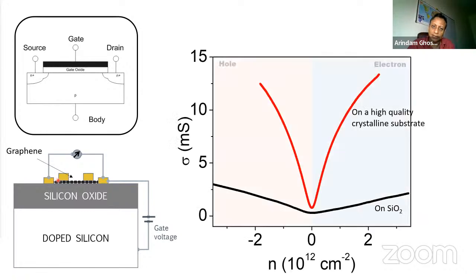What was found is very interesting. In the case of graphene, as you increase the electron density by applying a positive gate voltage, you get the conductivity to increase. Again, that can be understood because you are doping graphene the way you dope any semiconductor. You dope graphene with electrons, and hence the electrical conductivity is increasing. If you put a negative gate voltage, now you are inducing holes in graphene, and hence the electrical conductivity goes up again. So this is the hole doped regime of graphene. Now I have put two different lines, which I'm going to clarify later. One is red, the other is black.